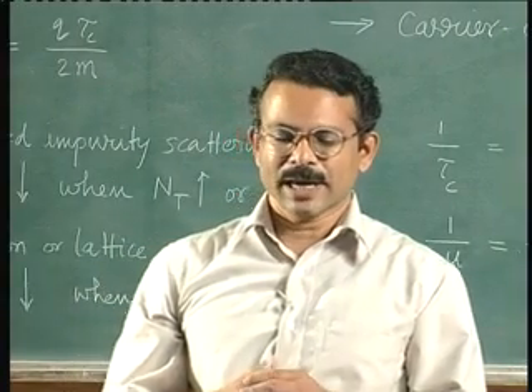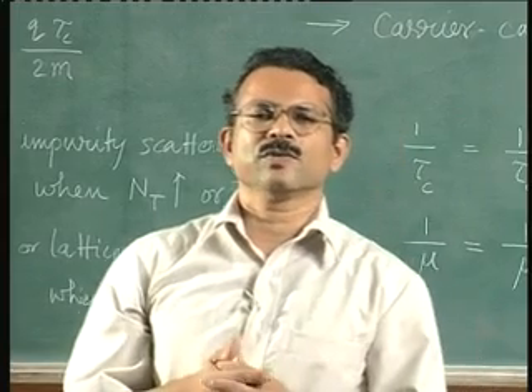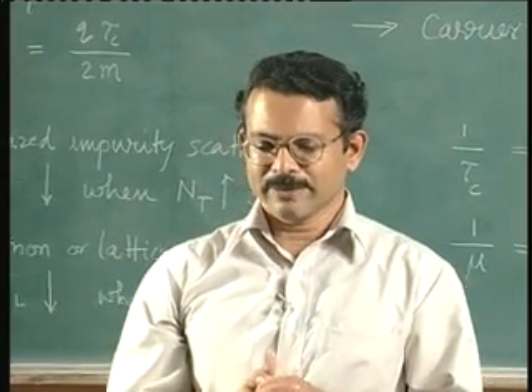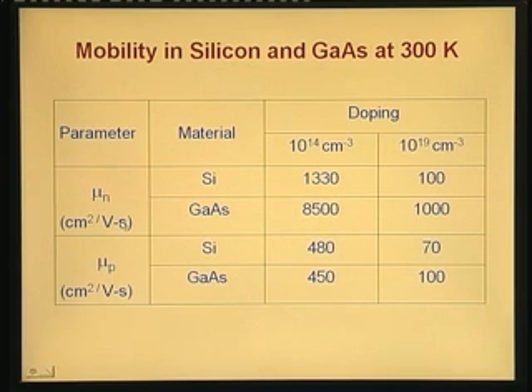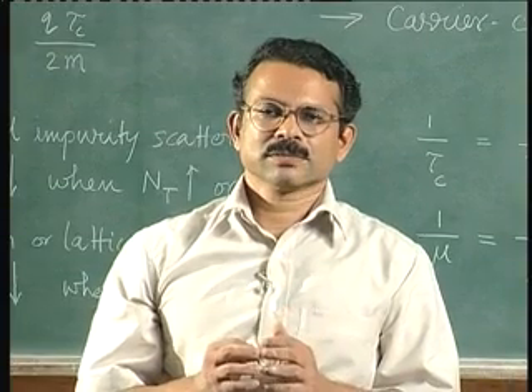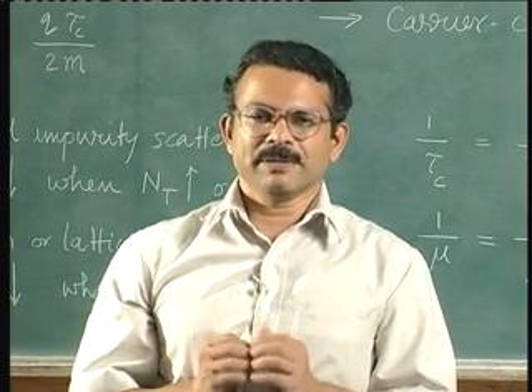So alternatives to silicon are being considered. Gallium arsenide is one such alternative for high speed devices or high power devices. However, you can see here that the hole mobility in gallium arsenide is comparable to that of silicon. Okay. In fact, it is lower at 10 power 14 per centimeter cube doping level. So this low hole mobility coupled with very high electron mobility creates some problems in the case of gallium arsenide if you are making circuits which require both n-type and p-type devices.